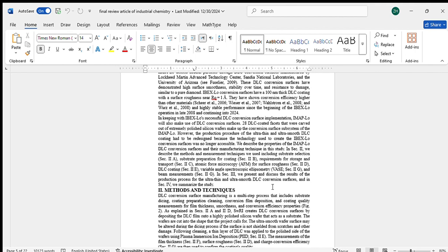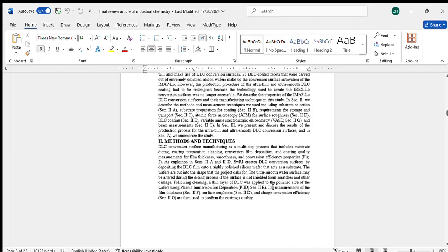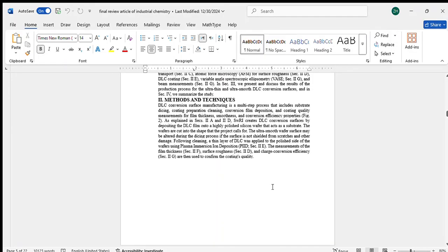If necessary, the coated surfaces are cleaned with deionized water and IPA to remove any particles that might have settled on the surface. For example, an AFM image is used to compare the surface roughness of the coated surface before and after cleaning. If large particles are present, the surface roughness can increase significantly, as shown in the image,